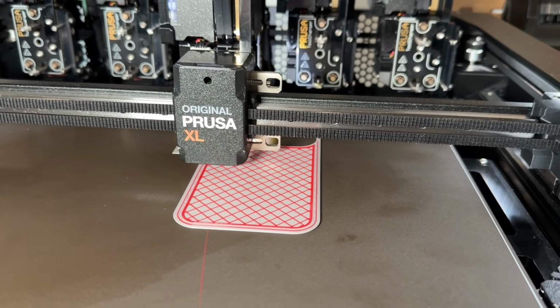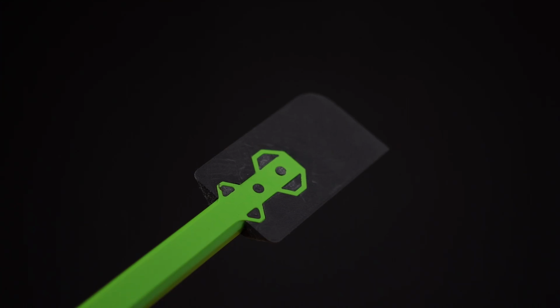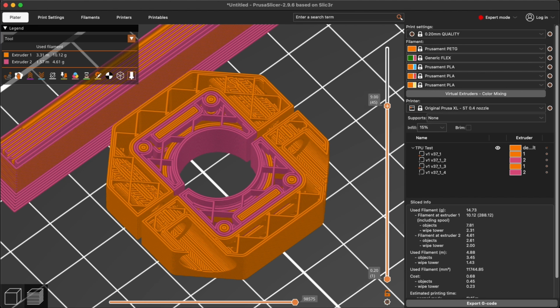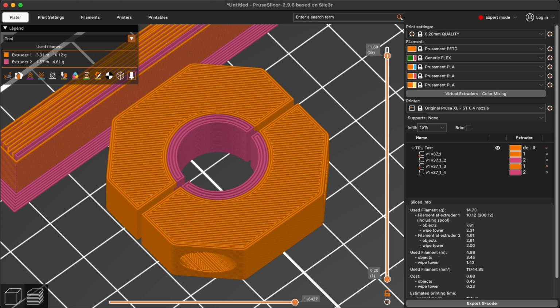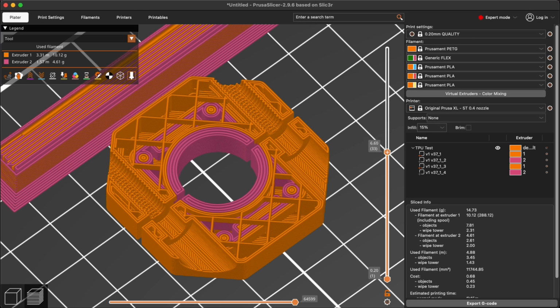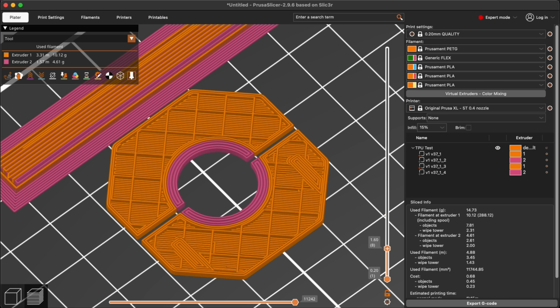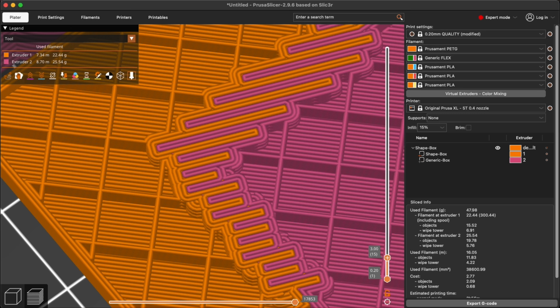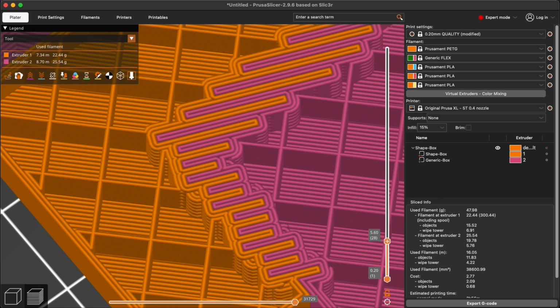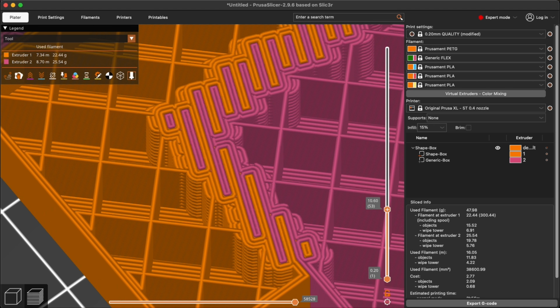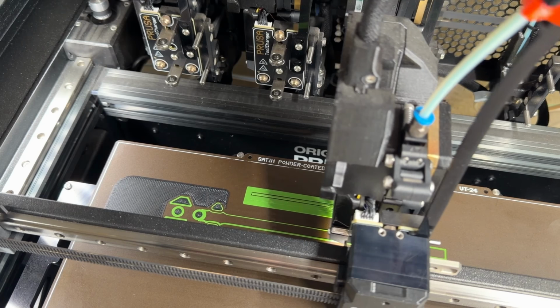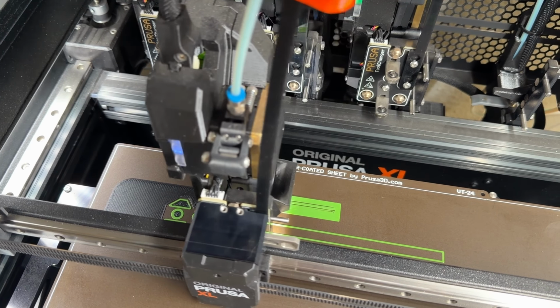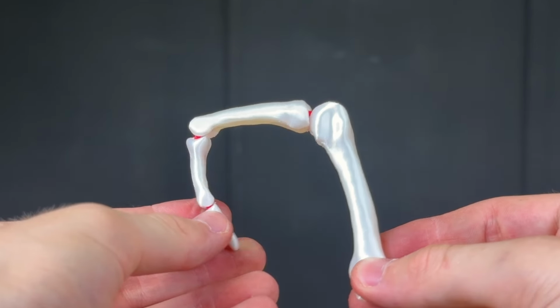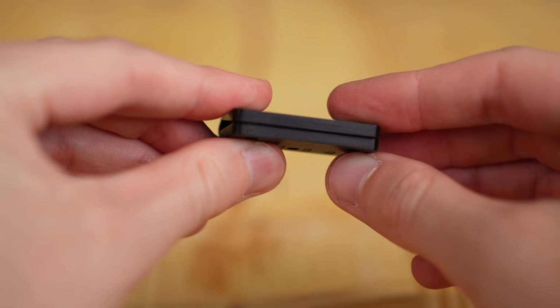TPU doesn't chemically bond to all filaments. A good fix is interlocking, a mechanical construction where the two materials physically lock together instead of relying on adhesion. Since version 2.9.1, PrusaSlicer does it for you. It builds a cross-hatched beam structure at the material transition, so filaments that normally won't stick, like PLA and TPU, hold together mechanically. This is great for education models or functional parts like hinges.